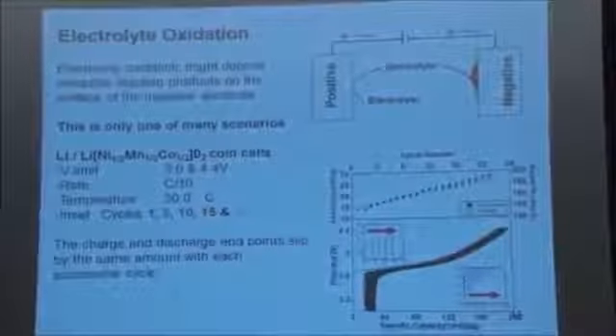Okay, so you can learn about these parasitic reactions by carefully keeping track of the endpoints and how they slip. And the positive electrode shows a similar issue. So here's a positive electrode, and when that electrode gets charged, the voltage goes quite high, 4.2, 4.3 volts versus lithium metal. It's a very oxidizing condition.